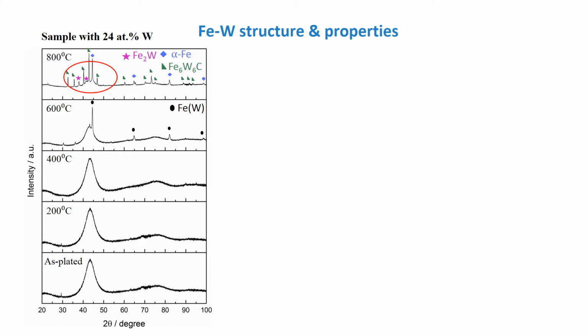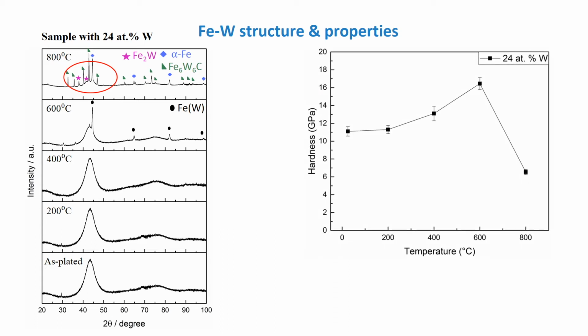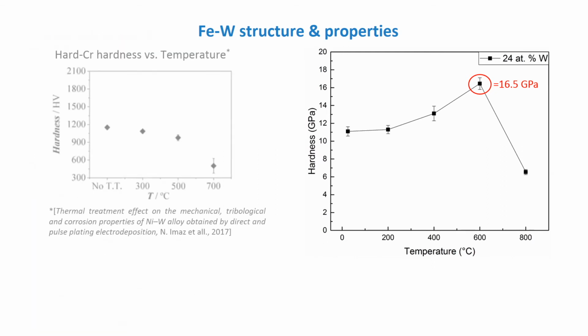The hardness of the coating upon annealing keeps increasing, and it reaches its maximum at 600 degrees with 16.5 gigapascal, which is a very good value, especially when compared to the hardness of hard chromium, which in the as-deposited condition, as we see, is around 1200 Vickers, which roughly corresponds to 12 gigapascal. But the hardness of the material keeps decreasing when the material is operating at higher temperature.